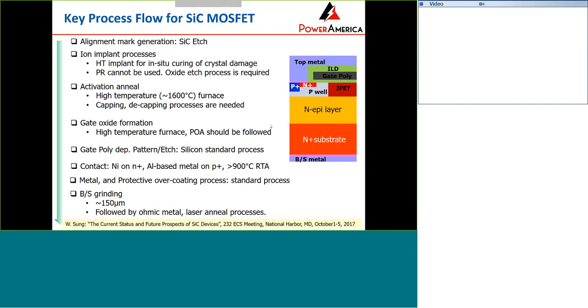Then you deposit the metal and protection. Normally, the backside needs to be ground off to some thickness to reduce the resistance component from the substrate. After that, use a laser anneal to make ohmic contact on the backside. So the majority of the process to make the silicon carbide MOSFET is identical to the silicon process, except the implantation, activation, and gate oxidation. Some ohmic contact processes for silicon carbide are also different from silicon.